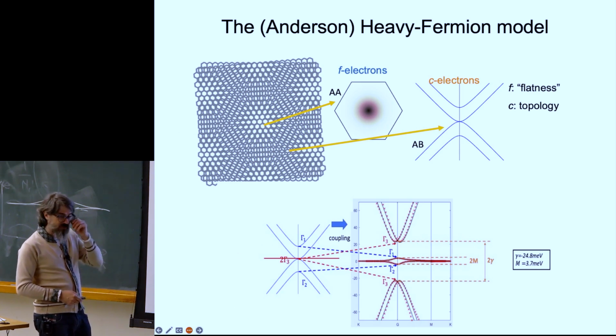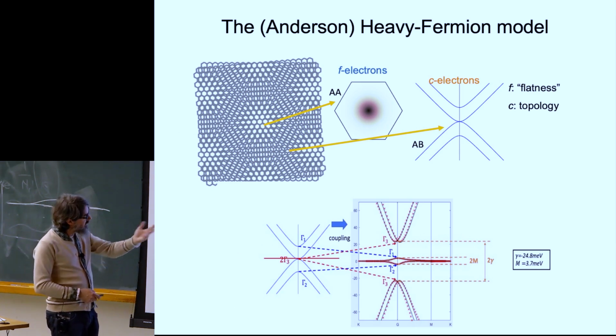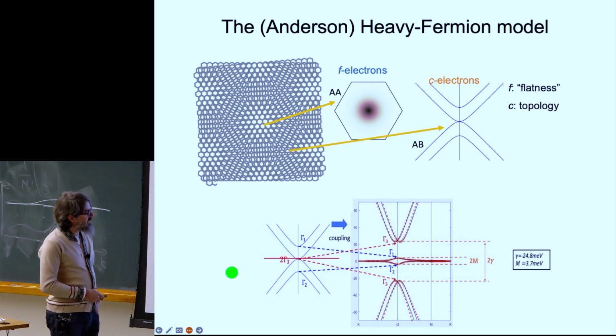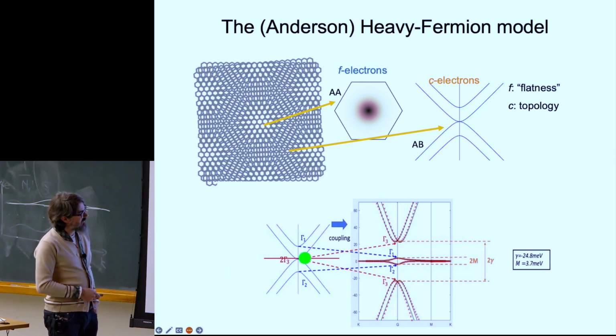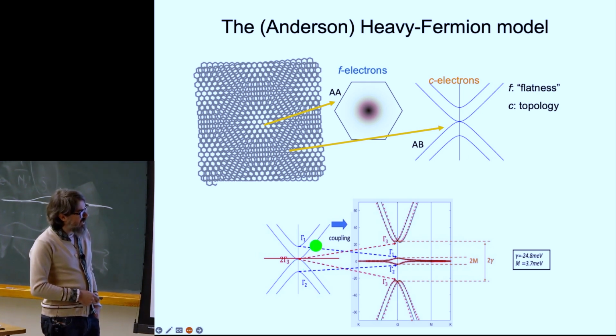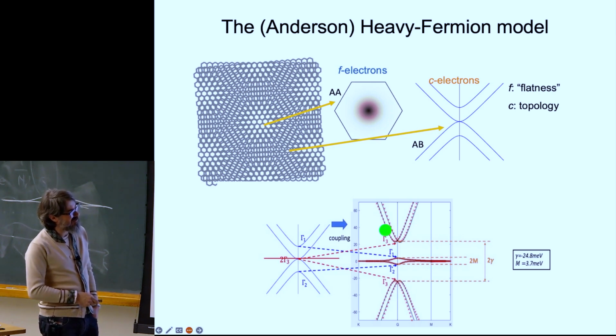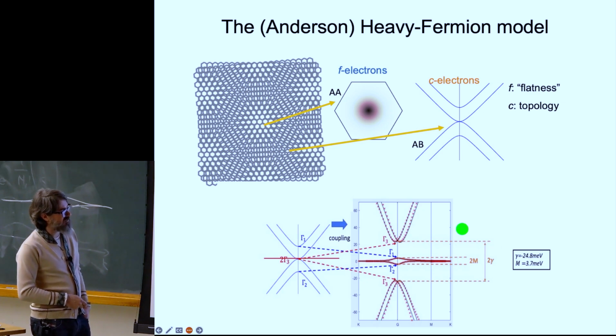Now you can say this doesn't look very much like what you showed me before. The only thing that you need to do, well, you're not putting it by hand, you're deducing it. Because this double vortex here and the F electrons have the same representation at the gamma point for condensed matter physicists, there's just a constant hybridization between them, and then bada bing bada boom, the bands become exactly these. So the red are our model, and the lines are the Bistritzer-MacDonald model. So you can match these bands, and this is a 6x6 model. This is a much larger model, so you can match this band structure exactly.